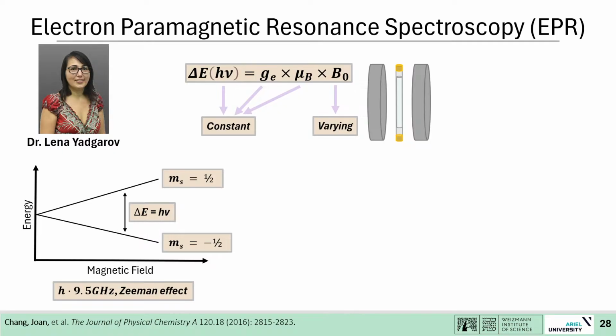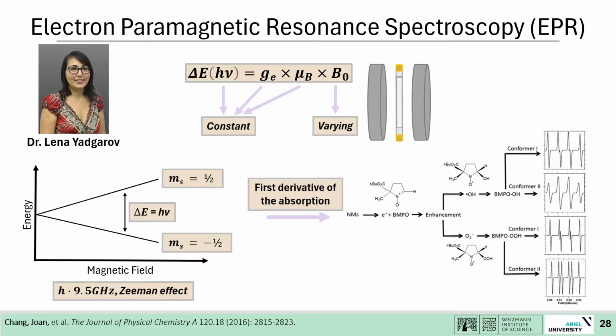When an electron is placed inside a magnetic field, it has a magnetic moment that will align parallel and anti-parallel to the magnetic field. Each will have a specific energy. So in these measurements, we keep all the parameters constant, the frequency, the Bohr magneton, the g factor, and vary only the magnetic field until we arrive at the resonance condition. In this resonance condition, the electron can absorb energy. And what we will see as a spectrum is the first derivative of the absorption.